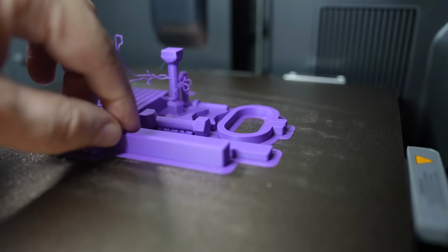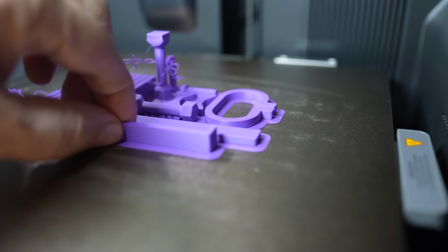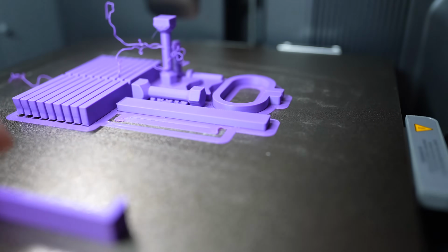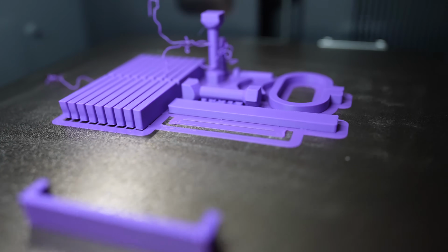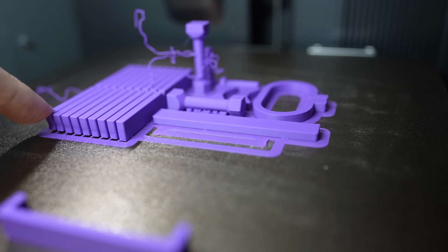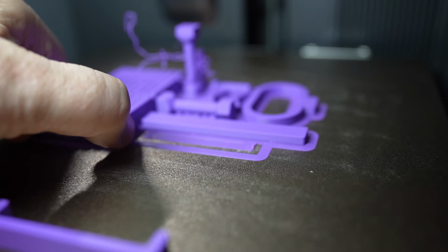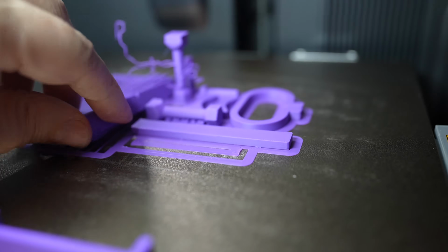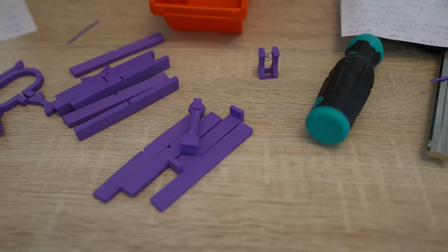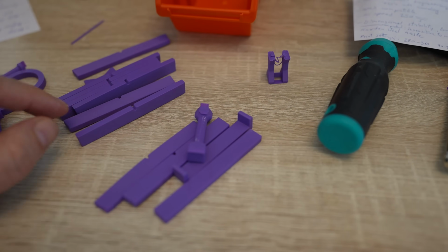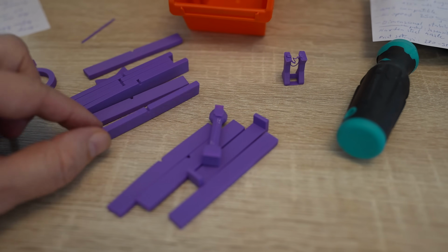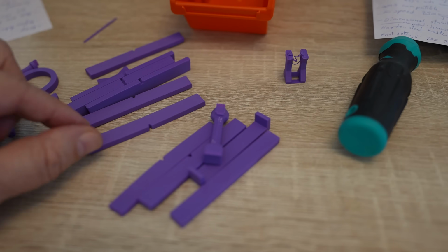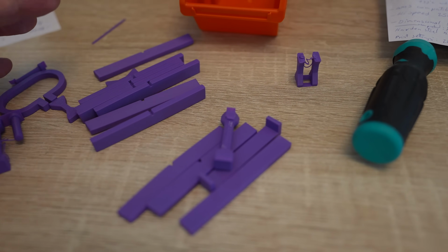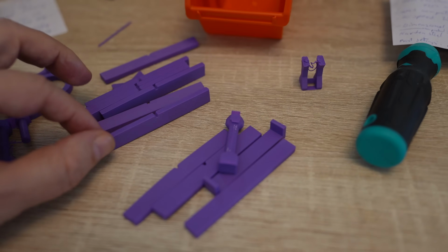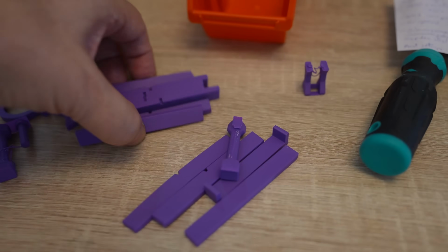And I checked, the bed adhesion is very strong actually. I cannot remove this. Oh, okay, now I can. But this warping means that it is very strong. Not big, but very strong warping because the adhesion is quite good. Another weird thing, few test objects for the impact test I took off quite early and now they are bent in a little bit different direction, some internal stress or something like that, so one of the hardest PLA for the printing.